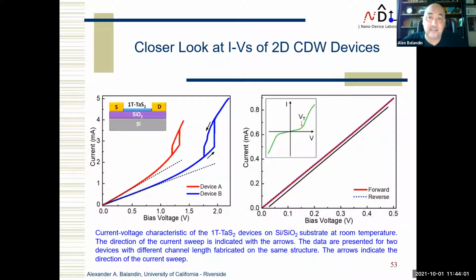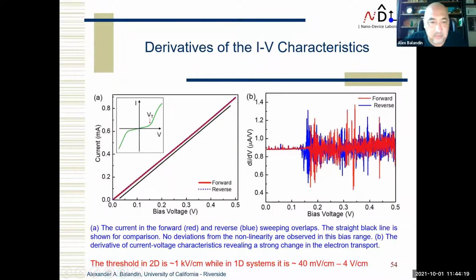However, we continued playing with that, and we finally just recently figured it out. If you look at these IV curves more carefully, I'm looking at the region which is still linear, right here. In this region, I was expecting a strong increase in current, and I have only a slight increase. You don't see anything. However, if you take a derivative, and you have to accumulate enough data points, take a derivative of the IV characteristics, something happens at a small bias. See, the bias is very small, 0.14, I think. Something serious happens in forward and reverse. We don't see it on the IV curve, but something actually happens here.